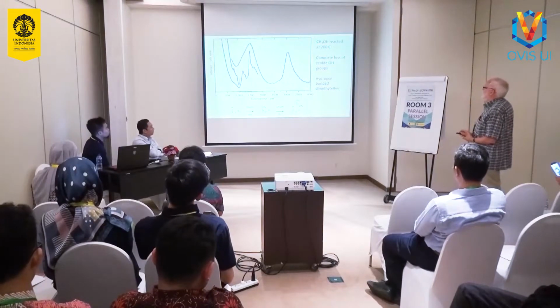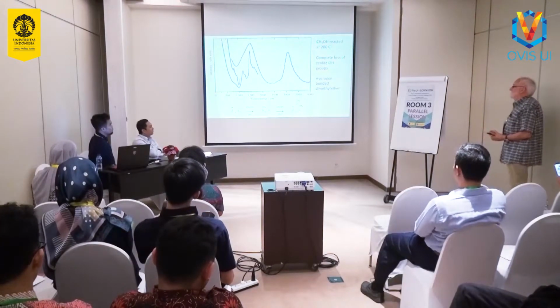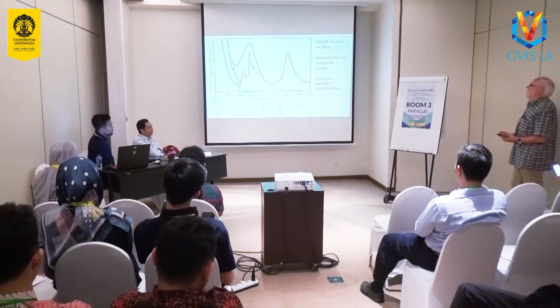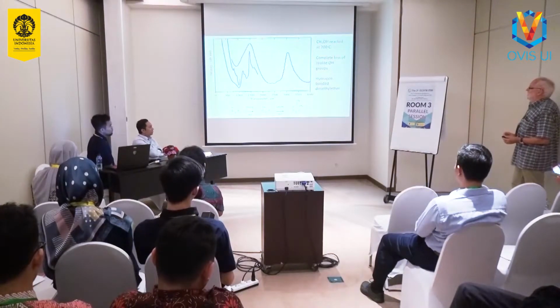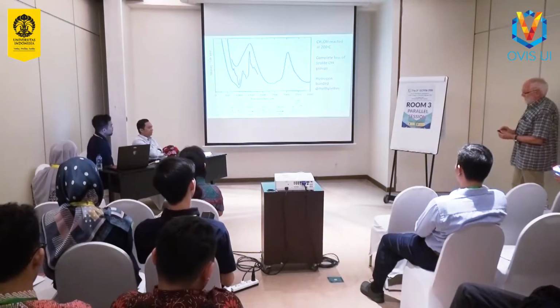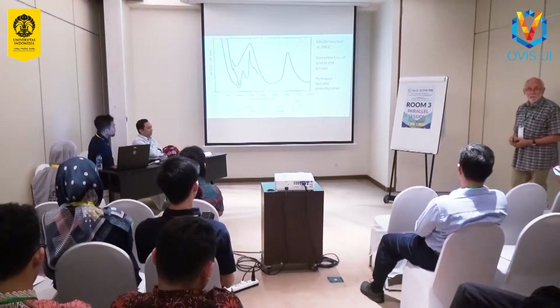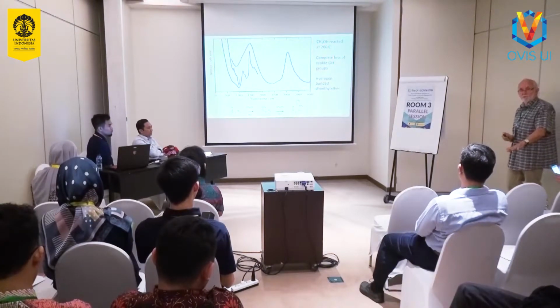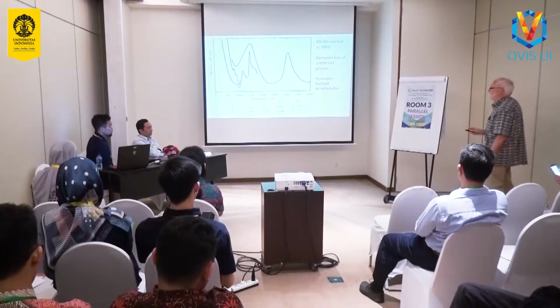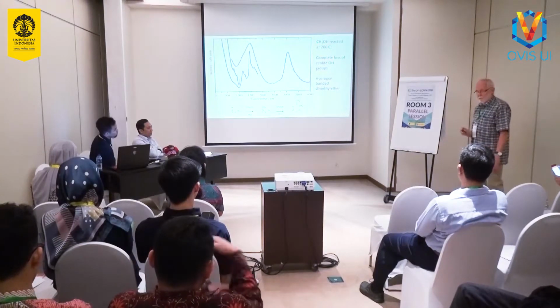Now let's do a reaction at low temperature, like 200 degrees C. So we run the reactor at 200 with methanol, and then we see what we've got. At this temperature we don't make hydrocarbons. This is below the threshold temperature for making hydrocarbons. All we make at this temperature is dimethyl ether.